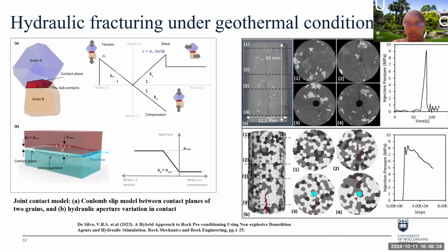This was produced using 3D software. The permeability of the grain assembly was matched to the intact granite matrix permeability by making grains impermeable, allowing fluid flow only between grain contacts. And we mimicked hydraulic stimulation on the intact grain assembly by considering compatible injection flow rates.